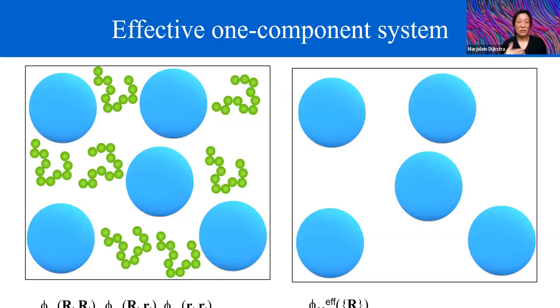And so what I've done is basically I've mapped a binary mixture of colloids and polymers onto an effective one-component system, so a colloids-only system, where the colloidal particles now interact with many-body effective interactions that depend on all the coordinates of the colloids. And this is an extremely complicated function because it depends on all the colloid coordinates, but with machine learning, we can just perform simulations of the full binary system, measure all these effective many-body interactions, and then use machine learning to fit this complicated high-dimensional function. And that is actually what we did.